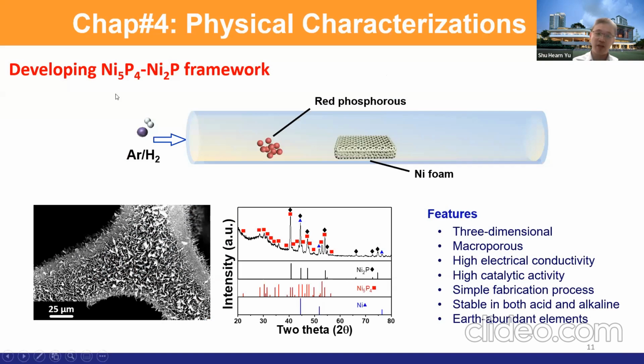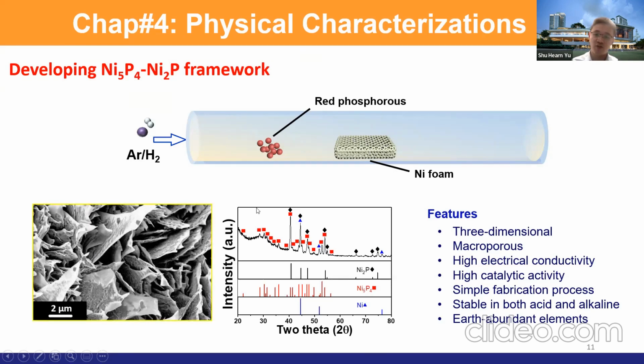So how do I fabricate? How do I develop the nickel phosphide framework? I apply red phosphorus with a nickel foam, under 95% argon gas with 5% hydrogen. And then after that, the red phosphorus can react with the nickel foam at about 500 degrees C. I find that at low temperature, for example 200 degrees C, the red phosphorus doesn't evaporate much. However, at around 500, I see that the nickel foam can interact with the red phosphorus and the nickel phosphide is formed. So these are the sheet structures of the nickel phosphide.